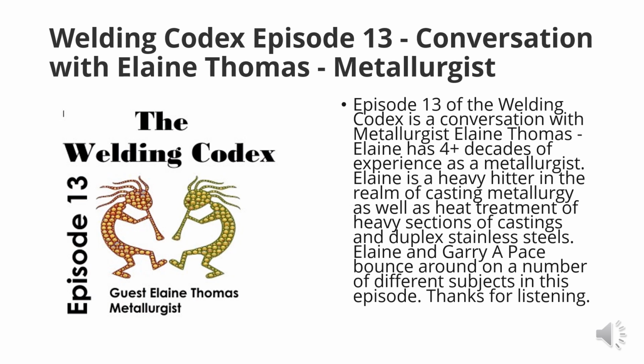So let's say I'm welding some duplex thin wall tubing. My chances of getting sigma formation are greatly diminished on that, aren't they? Yes, they are. That's going to cool off so quickly that there really is very little likelihood that it will form. So if I throw a little nitrogen in a back purge on a tubing weld, is that going to help? Sure, that'll help. Because the austenite phase is face-centered cubic, the nitrogen tends to fit interstitially, in between the atoms of chrome and moly and nickel and iron. The nitrogen fits in there very nicely. It doesn't supersaturate and it doesn't form bubbles.